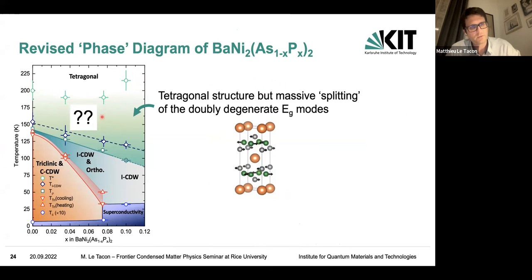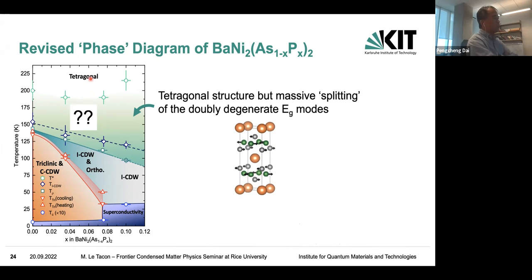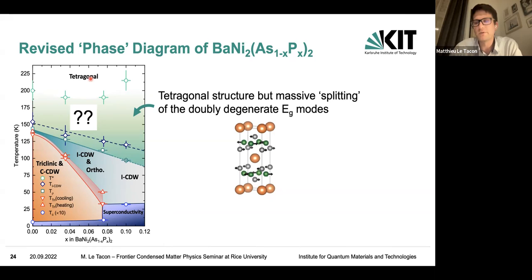And the question is, what's going on here? Because we do have a tetragonal phase, and in this tetragonal phase we do see a massive splitting of our EG modes. So basically, you're seeing the optical phonon split from one to two, even way above. Have you seen that with X-ray scattering as well? Because then you can determine its wave vector dependence. Yeah, I'm going to get to that in a moment. If you want a rapid spoiler, there is a soft phonon which is associated with this charge density wave, and the soft phonon is basically this phonon, at finite Q. So it's this mode that gets completely soft at the wave vector of the charge density wave. So everything's connected in a way.